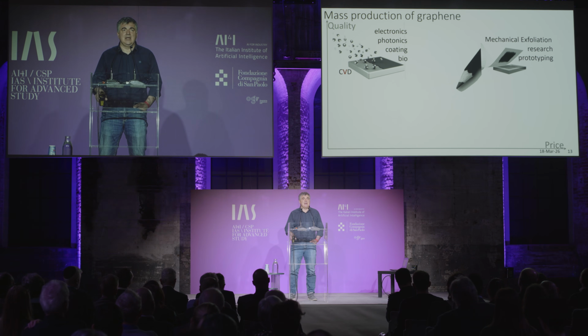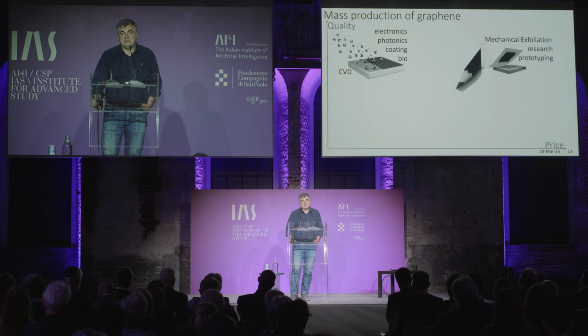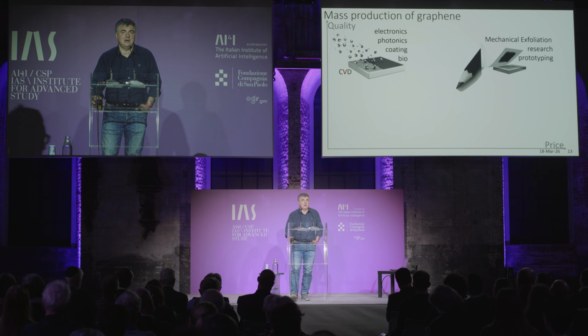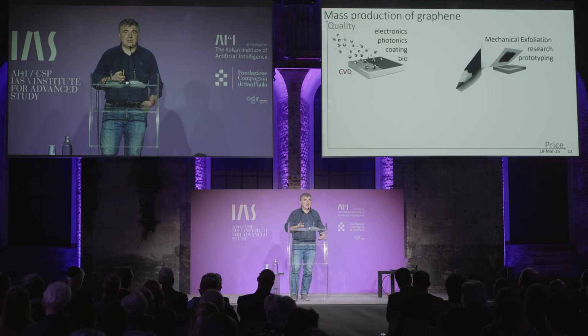You would use the so-called chemical vapor deposition. What you do is take a carbon-containing gas, like methane, for example, and you run it on top of a hot catalytic surface. Usually copper is used, but you can use some other metals as well. This gas cracks on the surface, the hydrogen flies away, and carbon rearranges itself on the surface. So it's a standard technique. There are many companies, Sony, Samsung, that have large fabs to produce this material by this method. And the beauty of the method is that it's pretty much agnostic to what kind of carbon source you use.